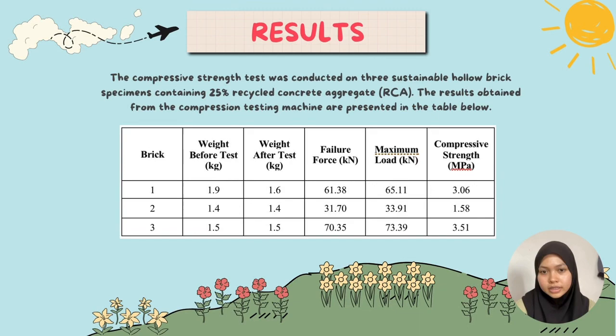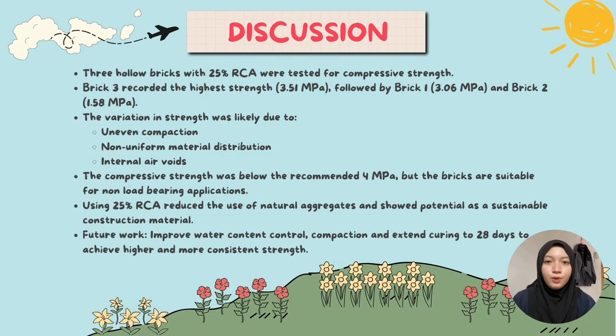Next are the compression test results. 3 sustainable hollow brick specimens containing 25% of RCA were tested. Brick 1 achieved a compressive strength of 3.06 MPa, while Brick 2 recorded the lowest value of 1.58 MPa. Brick 3 shows the highest compressive strength of 3.51 MPa. From these results, we can conclude that Brick 3 performed the best under the compressive loading. The differences in compressive strength between the specimens may be due to slight variations during specimen preparation, such as compaction and material distribution.